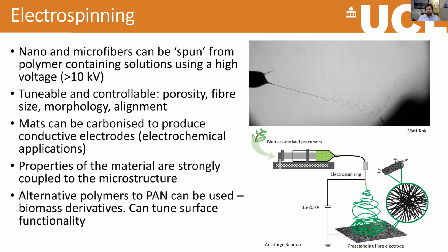So we get these nanofibers, which of course increases the surface area for reaction, which is really great. It also means that by changing the conditions of the electrospinning, we can control things like the porosity, the fiber size, the alignment of the fibers, and the morphology, which all play into the way that redox flow batteries work. So this is really key. Also means you can use alternative polymers, which can give you different surface properties in terms of their chemistry, in terms of their reaction catalyst. And also we can use more sustainable polymers that are derived from biomass, and that's a really key area of some of the work we do in conjunction with Queen Mary University as well.